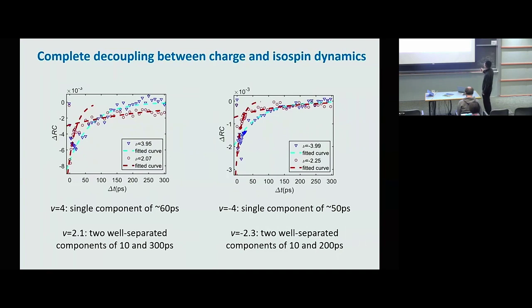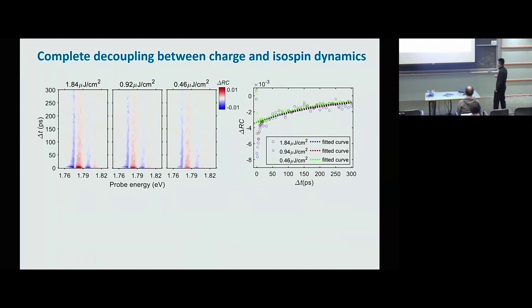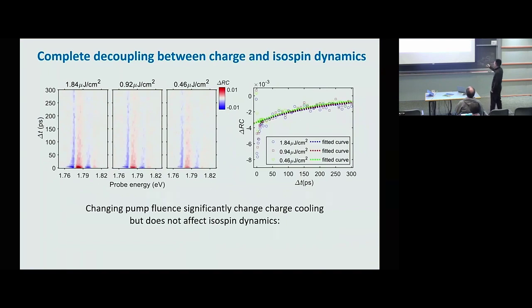And similarly, on the hole doping side, the minus 4 is also a single component, but minus 2.3 is 2 components. And this fast component is matching pretty well with the charge dynamics obtained in the other paper, but this slow component is much slower, it's completely decoupled. And the complete decoupling between the charge and isospin dynamics can also be confirmed from the pump fluence dependence. So here we are changing the intensity or the fluence of the pump pulse. We change it by 4 times, so it's a pretty big range. And this will significantly change the initial electron temperature, and it should change the charge cooling process significantly. And indeed, we found that the initial fast component is changed significantly if we change this pump fluence by 4 times. However, this slow component doesn't change at all.